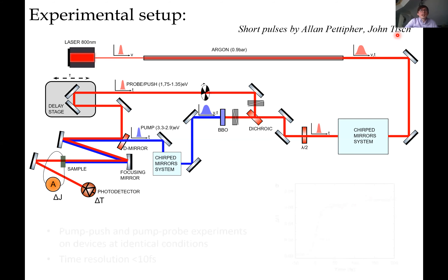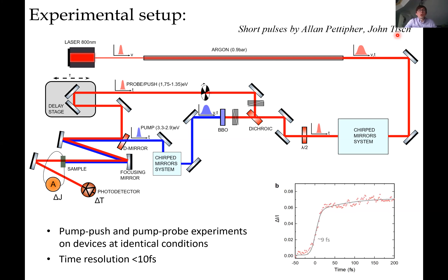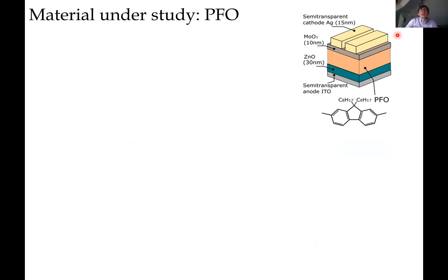We achieved sub-10 femtosecond time resolution — we hope that 10 femtoseconds is faster than even low-frequency intramolecular vibrations, which happen on longer timescales. This is really fast. We used this setup to study exciton formation in the well-studied material polyfluorene (PFO) with very high time resolution. We chose polyfluorene because we wanted something blue-absorbing and it was the most studied blue-absorbing polymer we had in mind, so this is a model study, not a new fancy material.